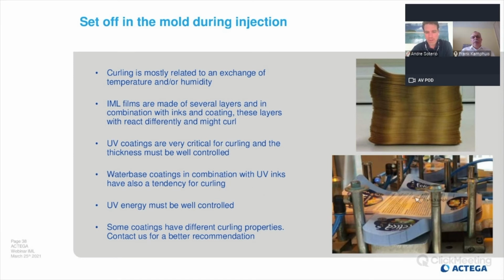So if you have curling of the labels, then you can't fill the station in a proper way. And mostly it depends on the label itself. That means you're using films, and in these films there are several layers. Then you add ink and coating on top, and then you get more layers, and that could cause curling through differences in temperature and humidity. So it's very important that you check your conditions, that the air is not too dry, but also not too humid. And because of the intensive energy you bring in by UV curing, UV coatings are more sensitive to curling compared to water-based coating.